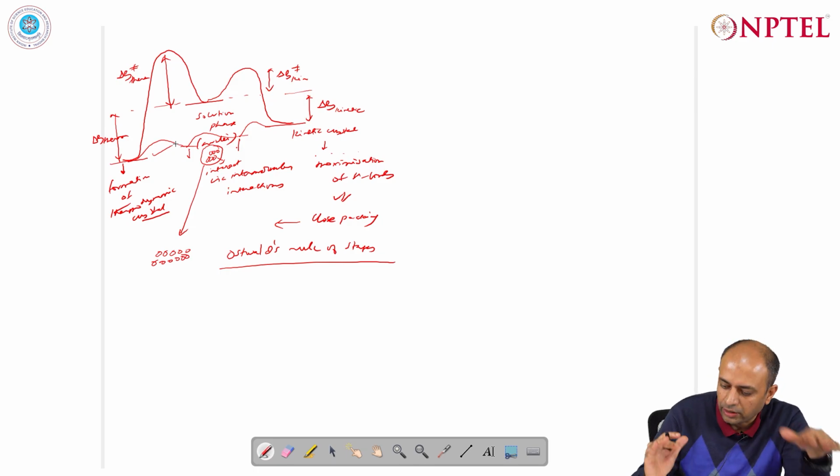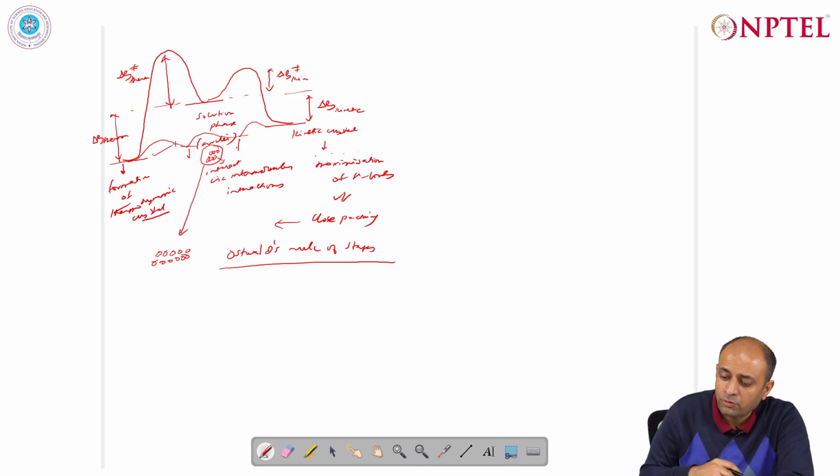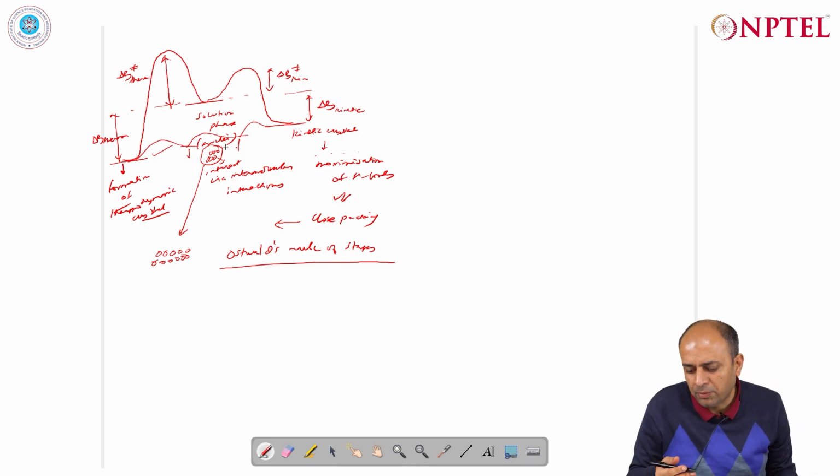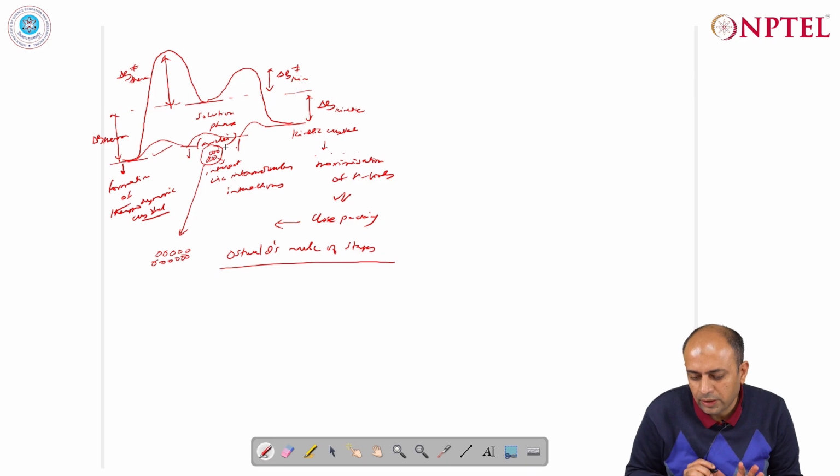into the thermodynamic crystal. And this thing is also very common when you take a kinetic crystal and dissolve it in solution, and you stir this mixture for a period of 2 to 3 days. The possibility of converting into the other polymorph is very high. That is, you can access the neighboring polymorph. It can be another kinetic polymorph, and if you do this stirring for a long period of time very slowly, you might end up converting into the thermodynamic crystal as well. So all these processes talk about the relevance of nucleation and growth.